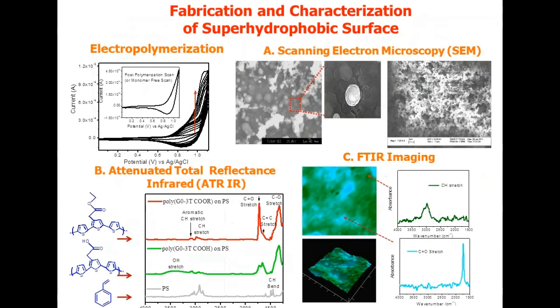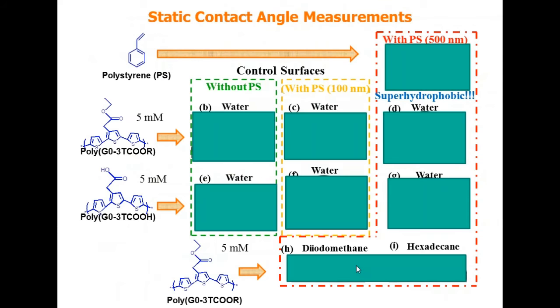Now, in our case, we actually utilized a film structure out of an over-deposition or over-polymerization of a surface with a polymer that we electropolymerized, as shown here. The terthiophene with an ester group or terthiophene with an acid group, and the same tools to investigate their morphology with SEM or IR imaging to determine the chemical function and distribution. And these are a summary of the wetting experiments that we conducted.